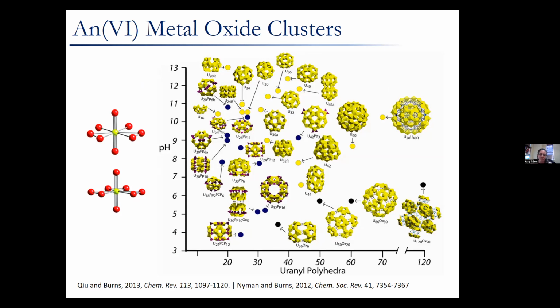The data points that are yellow represent uranyl peroxide nanoclusters that only have uranyl peroxide polyhedra, whereas those in the dark blue have also incorporated other species such as pyrophosphate ligands, or the black data points, which represent the inclusion of oxalate to basically provide some functionality to these nanoclusters.